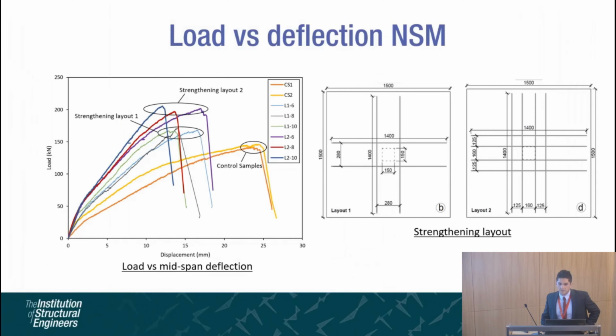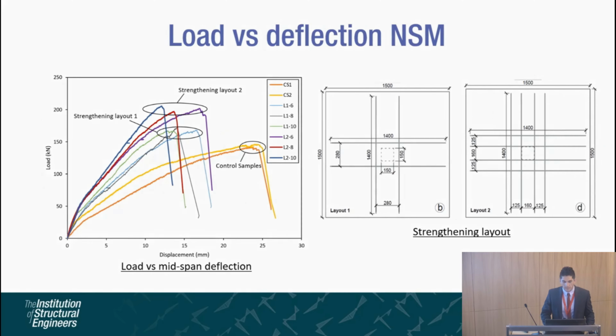With the near surface mounted method, as we can see, it maintained a very strong bond with the concrete. No debonding occurred during the failure. As we can see, a considerable increase in ultimate load could be obtained with strengthening layout number 1, even though it had only 2 FRP reinforcement in each direction. On average, it increased the load by up to 18%. With strengthening layout number 2, on average, it increased the load by up to 41%. So the amount of increase in load and its stiffness is directly proportional to the layout and to the number of reinforcement placed in the slab.